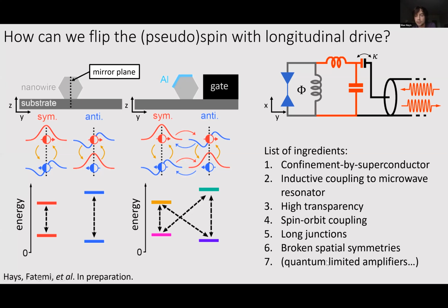So there's a bunch of ingredients we need here to get this, but in the end, this is the main point, that this is all mixed up and we should be able to drive the spin flipping transitions between the doublets. However, the direct spin flip transition will still be suppressed compared to these other ones, basically due to perturbation theory arguments.